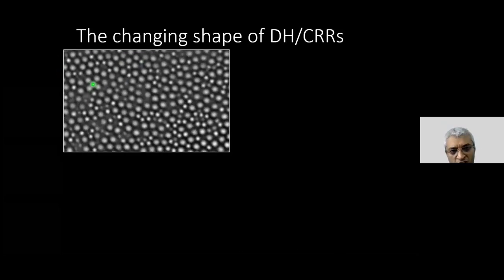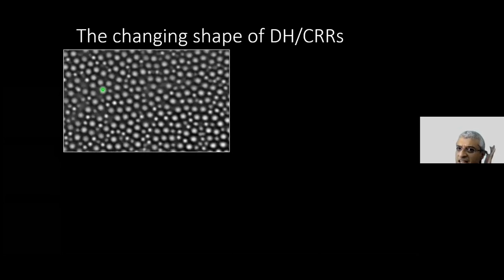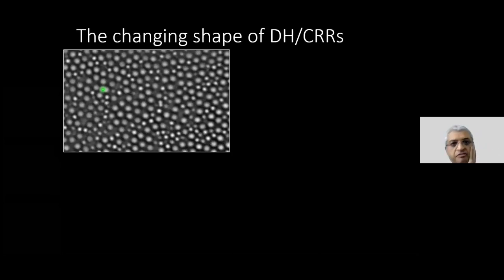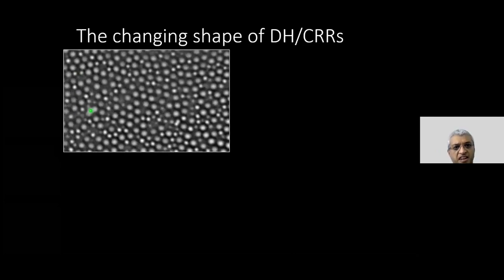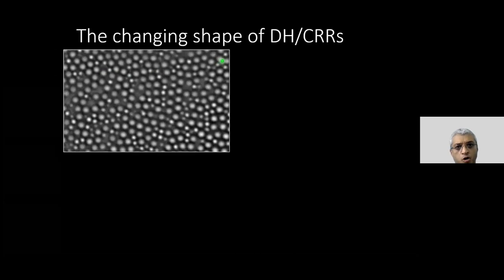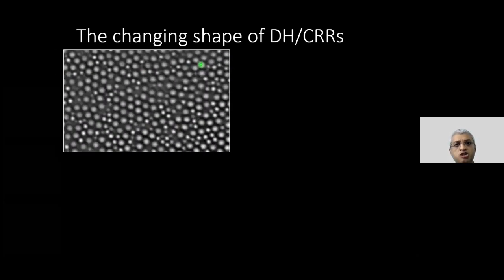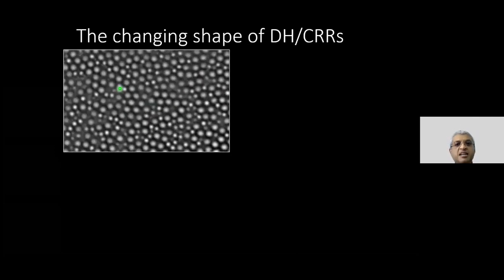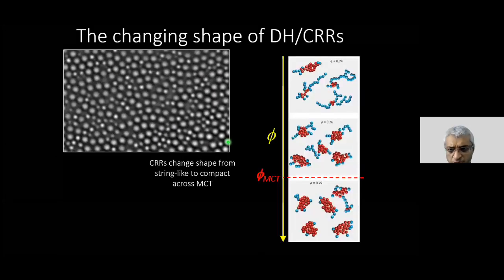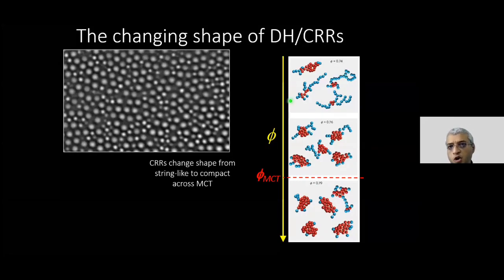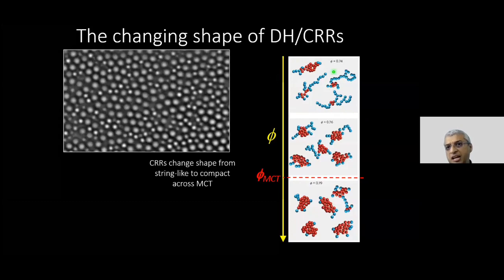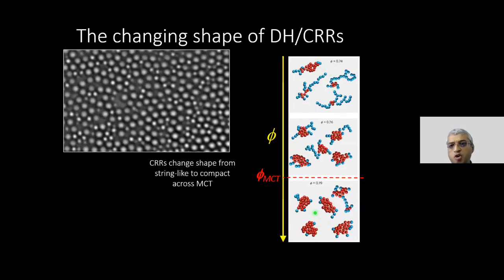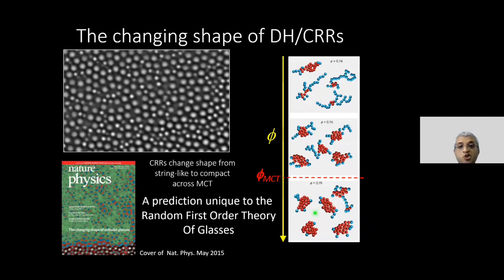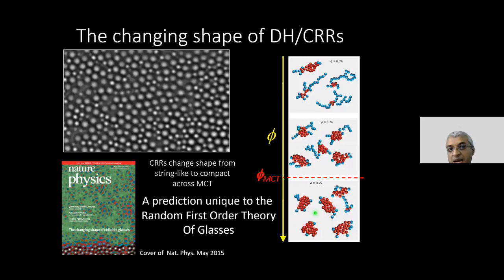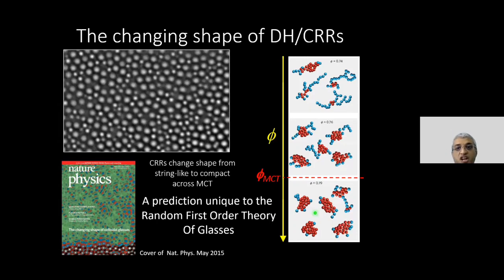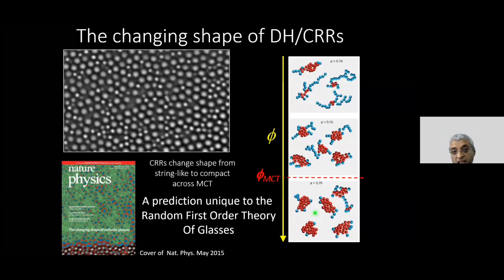So one way to probe these sort of dynamical heterogeneities, and also to get a better feeling for which would be the correct descriptor of the glass transition, is we took this glass and we froze a wall of particles. Okay, so this is a wall of particles frozen using an optical tweezer, and we basically quantified dynamical heterogeneities far away from this wall. Now, what we found is, as you increase the volume fraction, these dynamical heterogeneities basically go from more stringy shapes to more compact shapes, and that is a prediction that is unique to the random first order theory. So although they fit the relaxation time data equally well, only one theory captures this essential part of what the dynamical heterogeneities do, right?